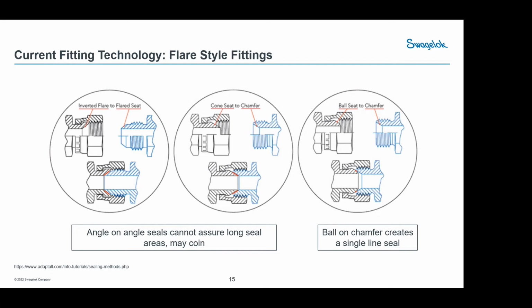And then on the end here, you see this one that's a ball end. This has become fairly popular in a few different designs on a different type of fitting because manufacturers like the fact that you can get some misalignment and it kind of works like a ball and socket joint. The problem is that if you go back to elementary school geometry and think about putting a ball inside of a cone, what you'll find is that you end up with a single line of contact again. So balls into cones is a single line of contact, and on hydrogen, that's really something we want to be avoiding.